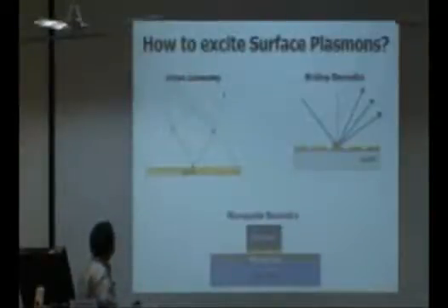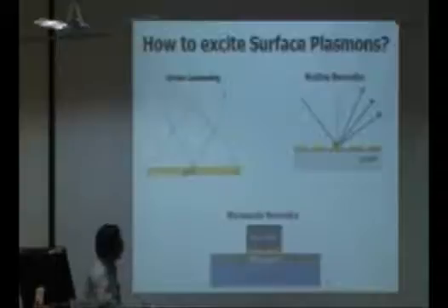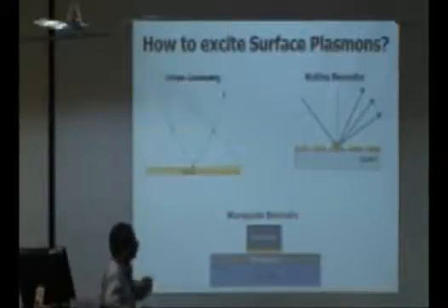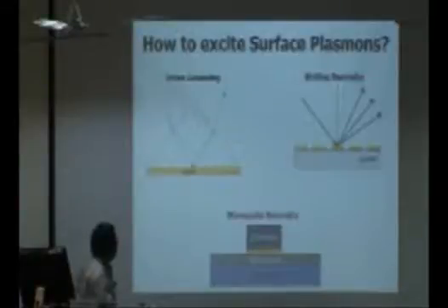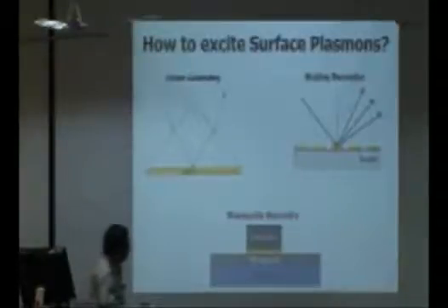The most used is the prism geometry, where above the critical angle, so basically total internal reflection, there is a small component which passes across this interface, which excites the plasmon mode. Okay. And the other one is the grating geometry. So here again, the angle is chosen such that one of the grating orders, one of the grating modes, excites the plasmon mode or the surface mode. Okay. In these two geometries the main problem is that there is an angle dependence. Okay. So it's basically the angle that defines the plasmon mode excited.